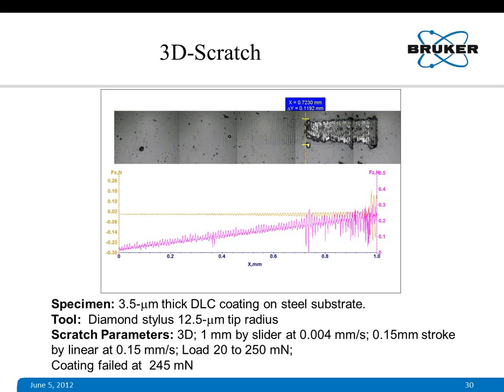But at the same time, the same specimen can move back and forth using the linear drive, which makes a series of very fine scratches, and the distance between two scratches can be well controlled using a script. By this process, you see at a certain point the coating started to fail. It delaminates, it scratches through the coating. You can see it on the optical microscope image on the top of it.